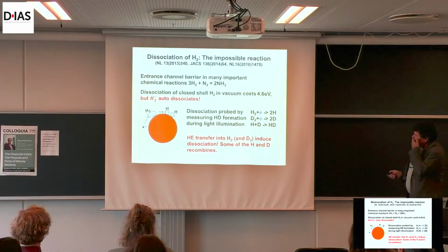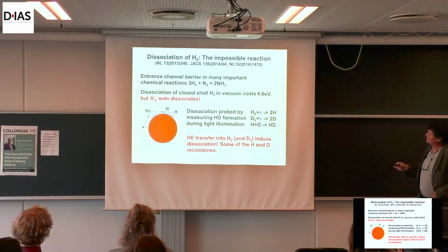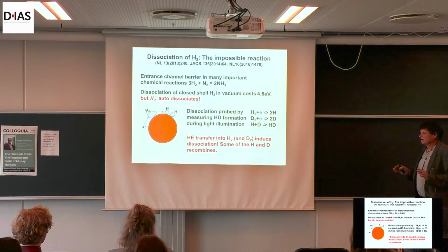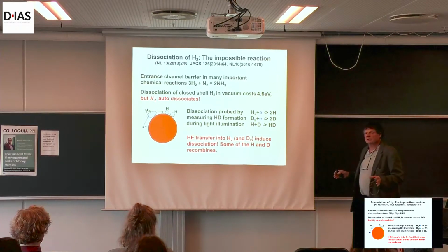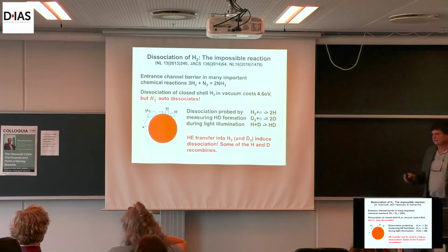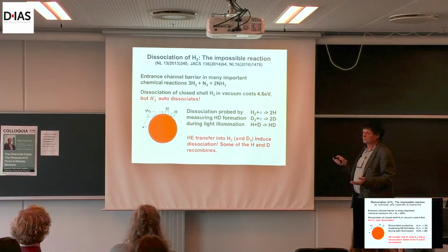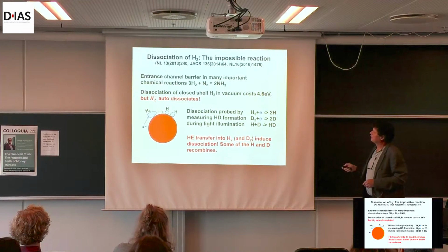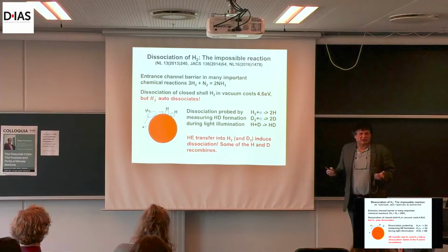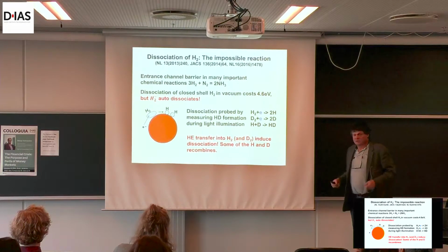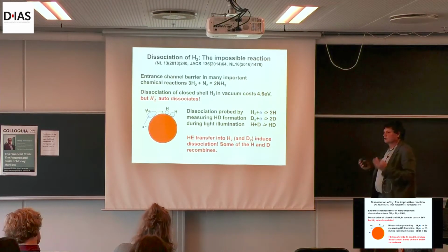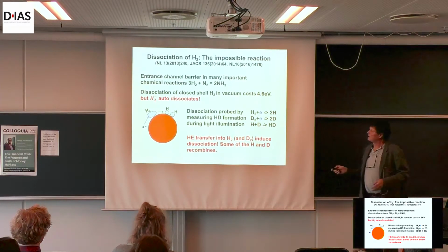So we did that in Naomi's group. So now we did this experiment showing that, in fact, you could dissociate H2. And that's actually something quite remarkable because an H2 for a physicist is the helium atom, okay? You look at it from a distance, it's 2 electrons. So it's very difficult to dissociate this, 4.6 eV dissociation. Now, if you form an H2 minus, okay, then it's very easy to dissociate. It auto-dissociates because that electron goes into an anti-bonding level. So long story short, we use this model reaction just to prove the existence of hot carrier-induced chemistry.